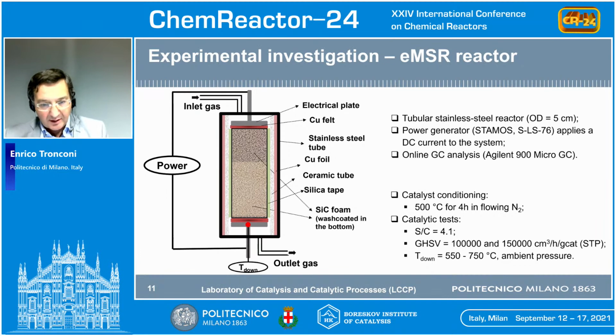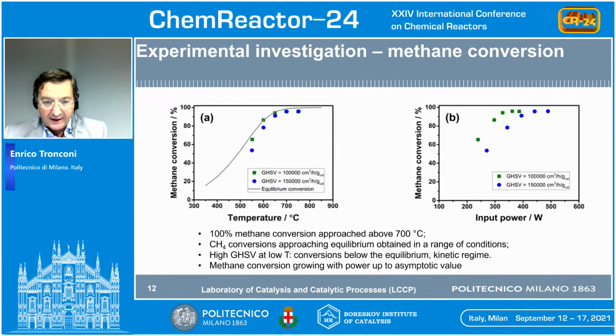Prior to any catalytic activity test, we condition the catalyst, and then we run catalytic activity experiments at ambient pressure at two different space velocities with a steam to carbon ratio of 4:1. And we operated the reactor at different outlet temperatures that were obtained by simply adjusting the input voltage of the power supply. Here are some results.